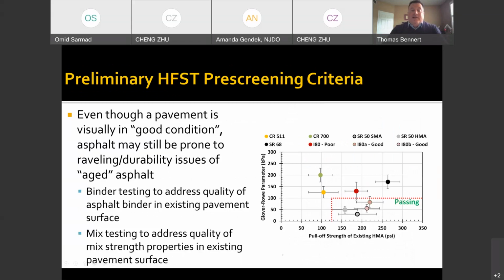And you can see over on the y-axis, you have that binder property. On the x-axis, you have the pull-off strength. And you can clearly see the passing area that you would need for these pavement sections and the failing area. And you could have, as I mentioned earlier, asphalt binder properties that in theory would have enough durability, but might just be too soft and would pull off. Or you can have a situation where the pull-off strength is very stiff and strong, but yet the asphalt binder properties are too stiff and would be poor for durability.